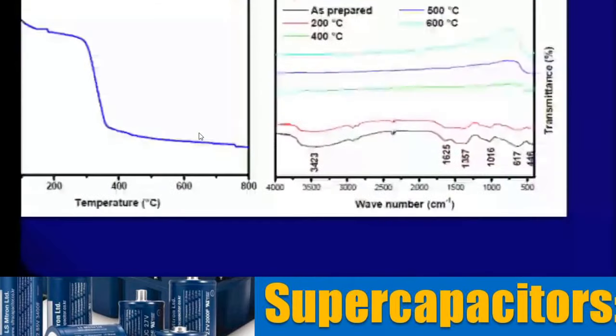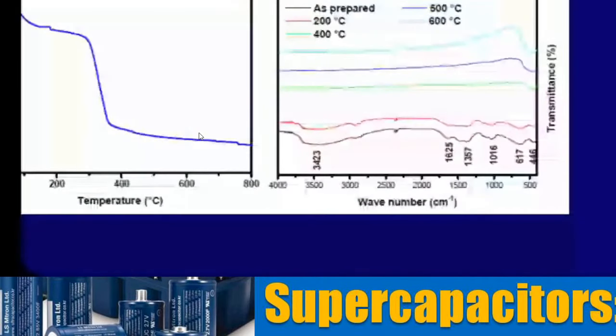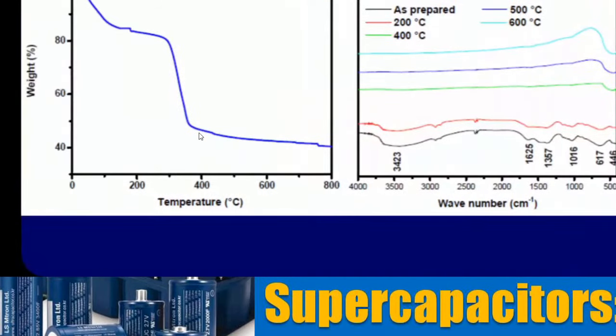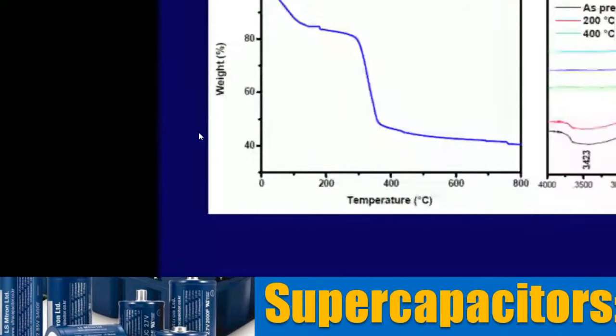So what has been done is, the material is treated at different temperatures, and we have taken the IR spectrum. You can see that at 600 degrees and below, it gives you vibrations of nickel hydroxide. Water is seen at 3423 centimeter inverse, and the water keeps on decreasing. At 600 degrees, or even at 400, the entire water is removed. Thermogravimetry can be used so that the energy budget for preparation is reduced, and 500 degrees is very good for our nickel hydroxide to nickel oxide conversion process.